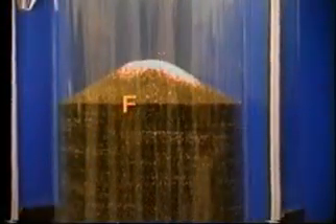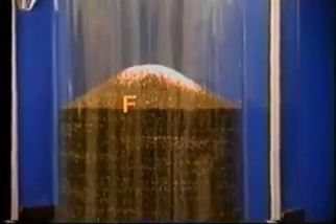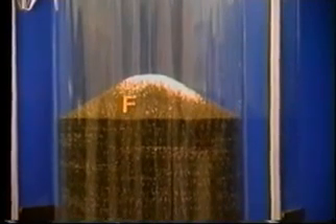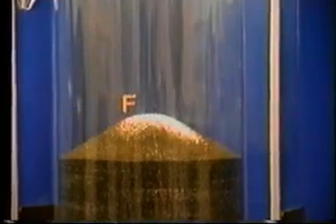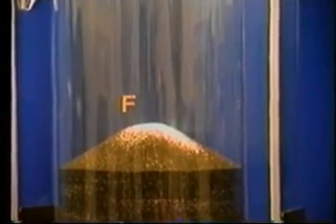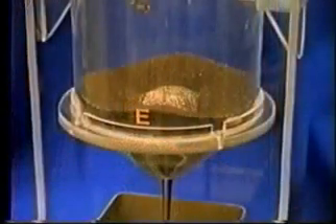The bottom gate is now opened and the sand exits the bin. The sand dome formed in the center of the bin does not immediately fold in. Instead, it rides down on top of the sand. This indicates the sand is feeding through all four openings in the inverted cone and going down level.